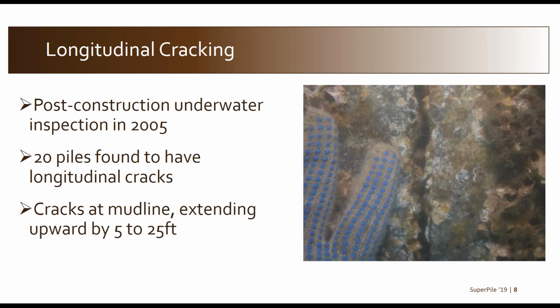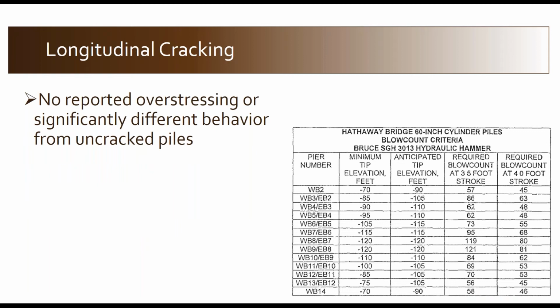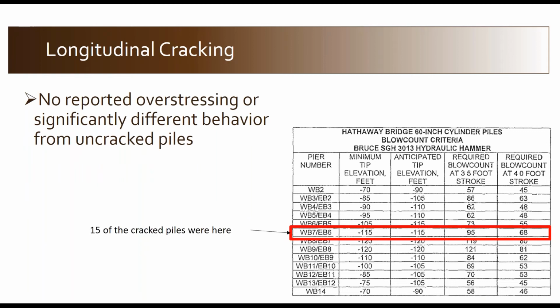Why did these cracks occur? Why didn't they occur on the other couple hundred piles? They only occurred on about 10% of them. So we started with the easy stuff. We tried to identify whether the ones that cracked were the longest or perhaps had the highest blow counts for the driving criteria. Maybe that's the easy explanation. Well, nothing's ever that easy.